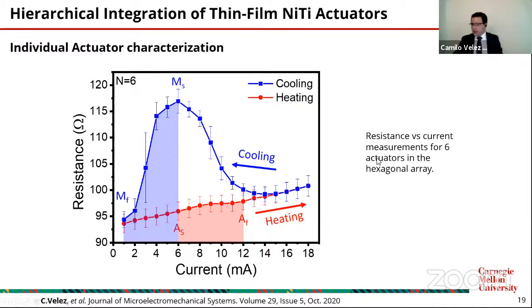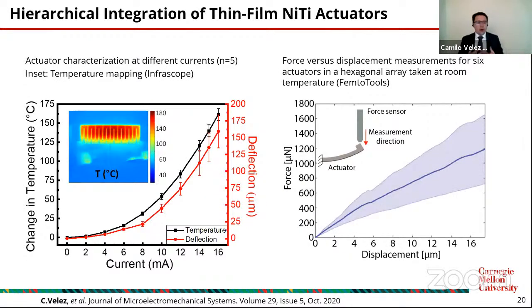Perfect. So I'm going to continue. And this was the resistance measurement for 6 devices in the hexagonal array. We also perform the temperature analysis, where we change the currents. Right now, we fix the thickness of the polymer that we want. We find the best one for us for having higher force. And we change the current to deflect them. We measure the temperature, and in a separate measurement, we measure the deflection, so we can correlate the deflection and the temperature.